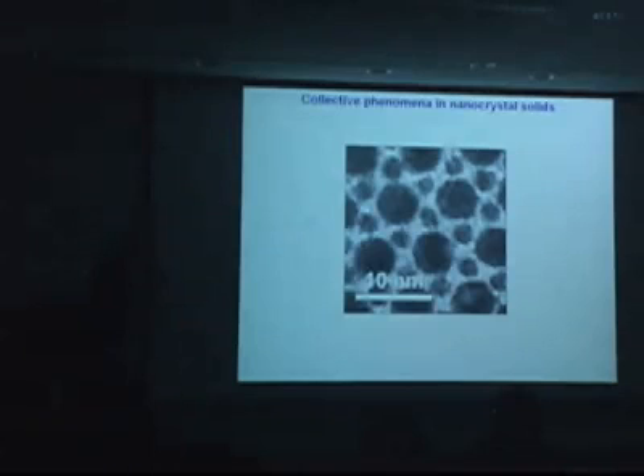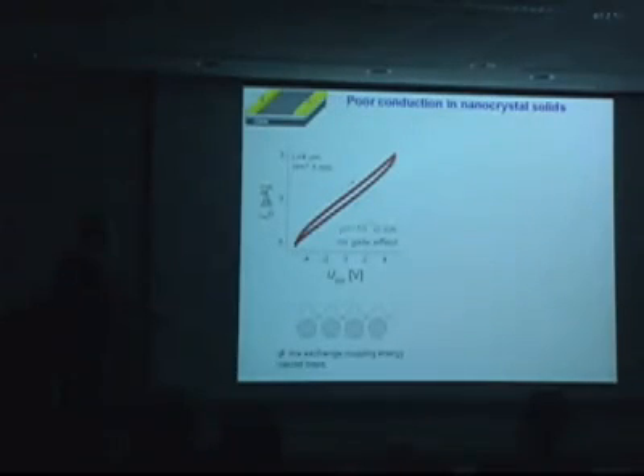And so from a chemist's perspective, it shifts the focus slightly from properties of the particles themselves to the interfaces, to the communication, to these areas that we don't see here, and to the role of surface ligands, or what is around the particles, the coating. Each layer of coating forms a tunneling barrier, and it leads to localization of wave functions on individual particles. And if we don't do the right job as chemists, we will end up with just insulating layers where, for example, we can bring together a semiconductor and a magnet, and they will not couple to each other. That's what happens when you use surface ligands that are necessary for colloidal synthesis. So just an array or film of colloidal particles is a very poor conductor.